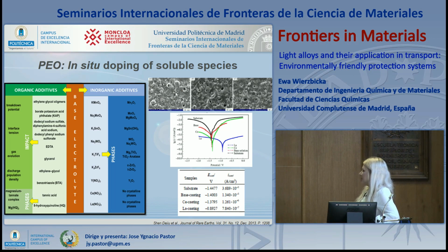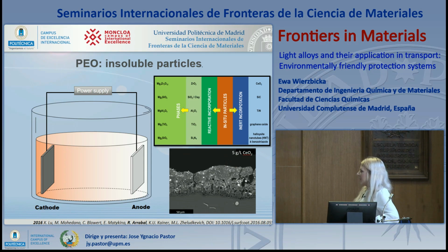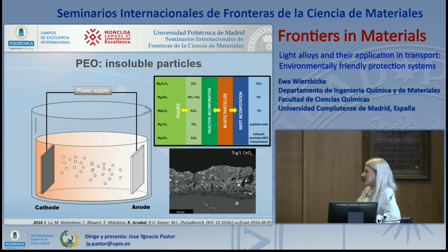and some crystalline phases. Even if the morphology of these coatings is not so different, we can observe that the presence of lanthanum or cerium improves the corrosion resistance of the coating. The electrolyte can also be modified by application of insoluble particles. Because PEO is such a high-energy process, they can be introduced into the coatings in the inert form or even in the reactive form, so the new phases will be the effect of the reaction with the metallic substrate.